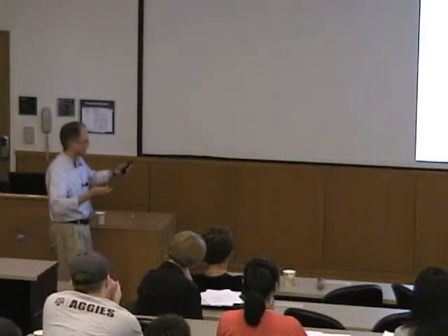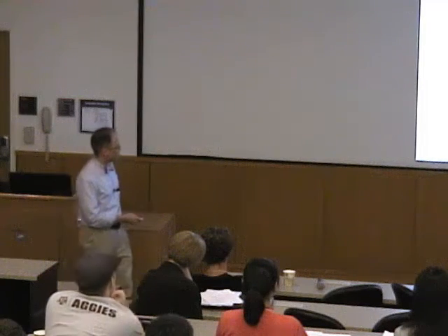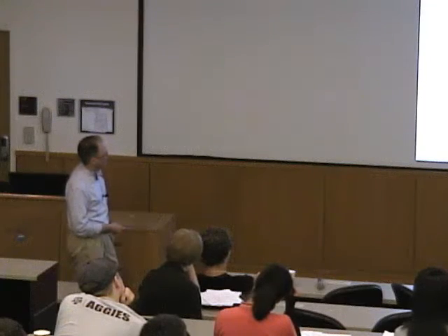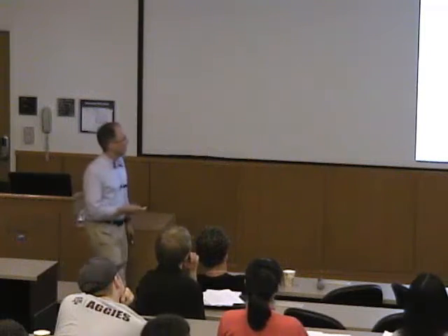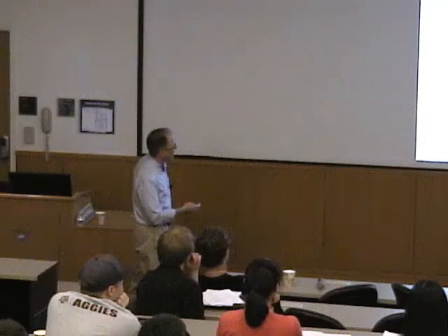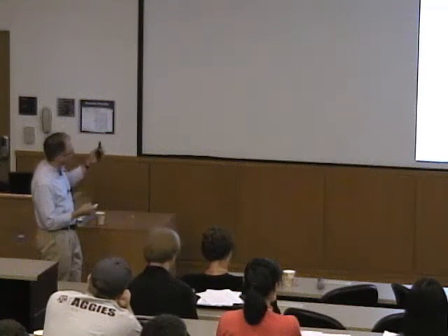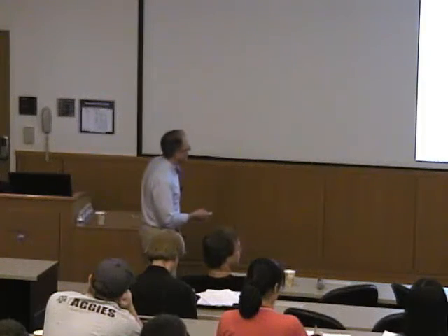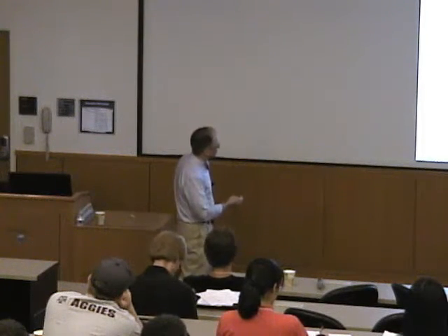And I know later on in the week we'll be hearing a lot more about the exact pathways and terms with which we can describe that sense of coupling, as well as how we can think more specifically about reorganization energy. If we're at an electrode, a similar relationship results. Although the typical behavior that is used for describing that rate of electron transfer, we can think in terms of first a Nernst equation, where there will simply be a potential-based dependence associated with that. And then an empirical, so-called Butler-Volmer model, which is a sort of tried-and-true model for electron transfer kinetics, would give rise to this type of result,